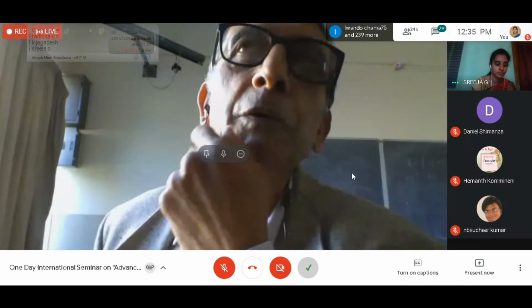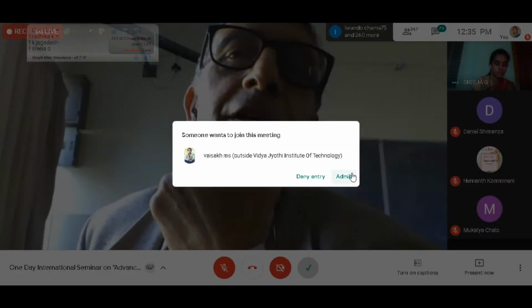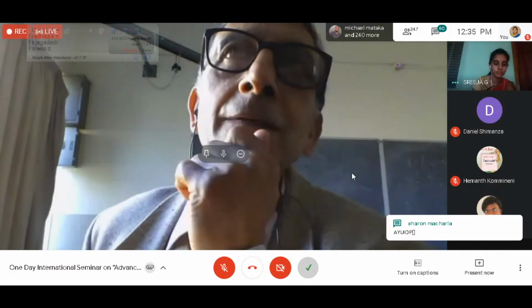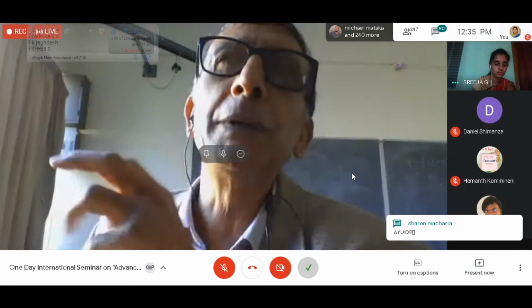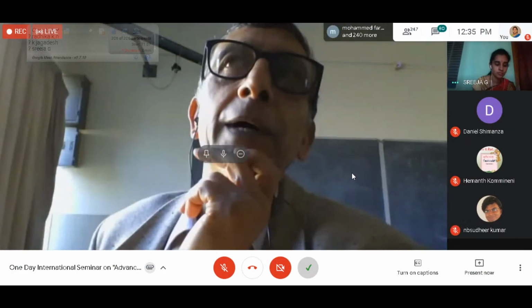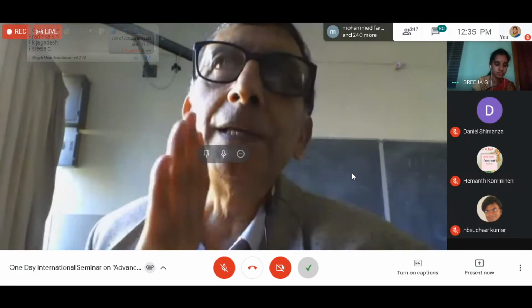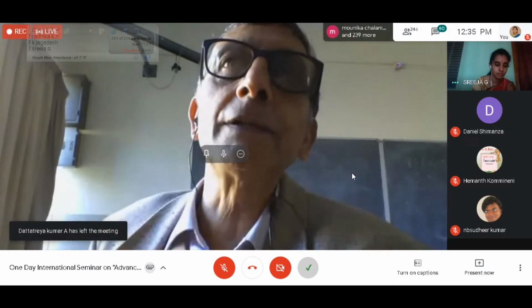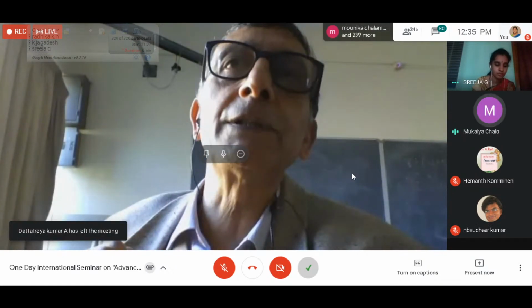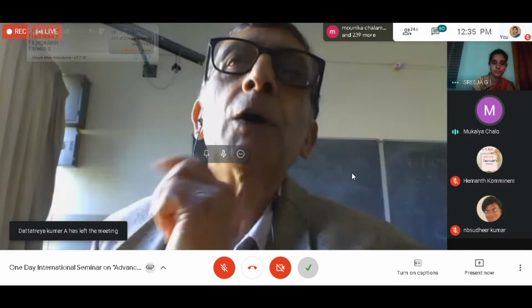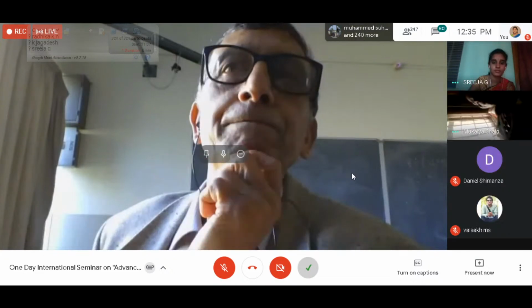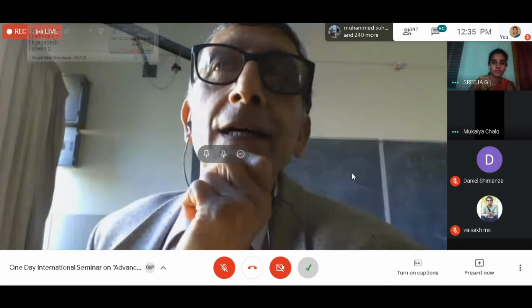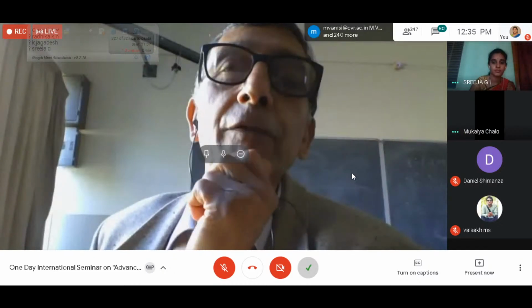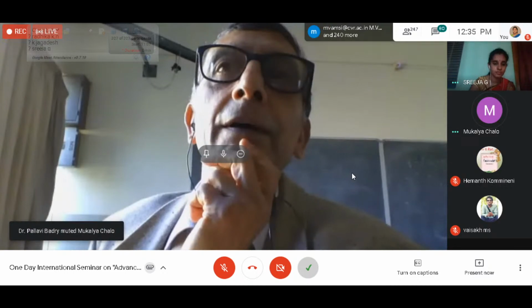That would not be an unreasonable first analysis approach. Your error would be that you are not accounting for the effect of temperature in stimulating hydration, but it would be a reasonable starting point in the way in which you analyze this. The point I'm leading to is that reducing the initial temperature, placing temperature of the concrete will reduce the maximum temperature. And so it is a good idea. So we've had projects where people have used ice as the mixed water in the concrete rather than water.